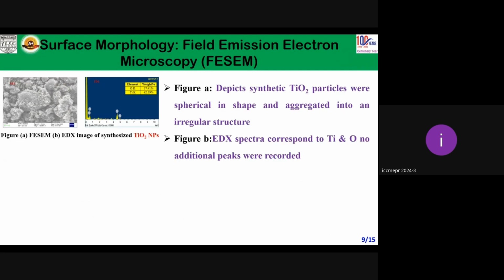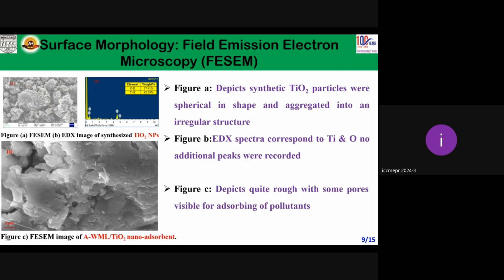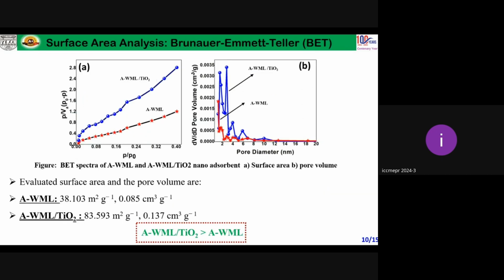Surface morphology was also studied for the TiO2 nanoparticle. Figures A and B show the FESEM and EDAX images of the TiO2 nanoparticle, which depict a spherical shape, slightly agglomerated into irregular structures. And EDAX clearly shows the spectra of Ti and O, which confirms that TiO2 is formed. Figure C shows FESEM images of the nanoadsorbent, which depict a quite rough surface with some pores visible, which are responsible for adsorption of pollutants.